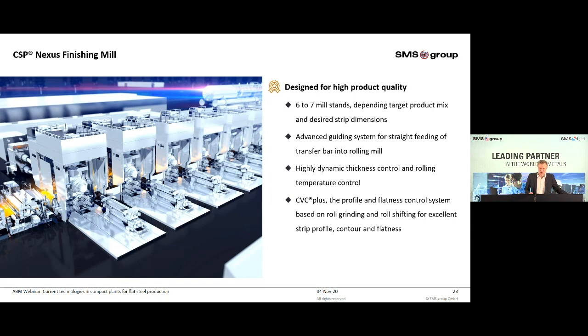The next slide shows the finishing mill with typically 6 mill stands. The advanced guiding system improves the center line positioning and increases rolling stability, especially during thin gauge production. Stable rolling of thin and wide high strength steel grades is supported by a highly dynamic thickness control. The strip temperature is controlled during the rolling process to hit the desired final rolling temperature. An integrated temperature model considers and controls the temperature profile along the entire plant.